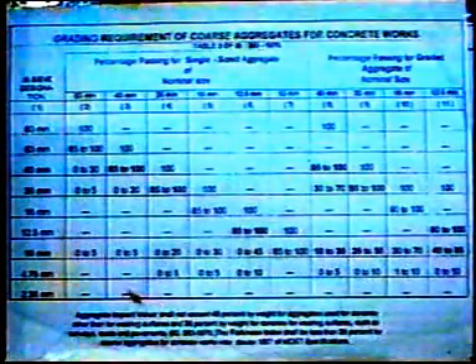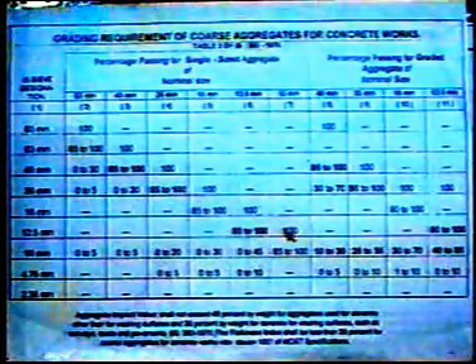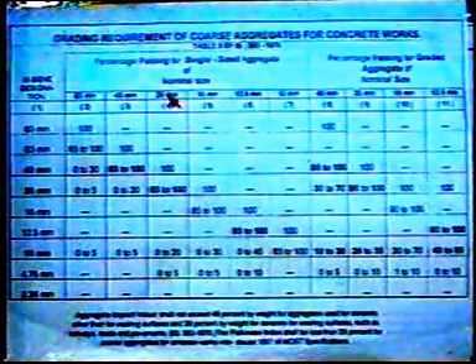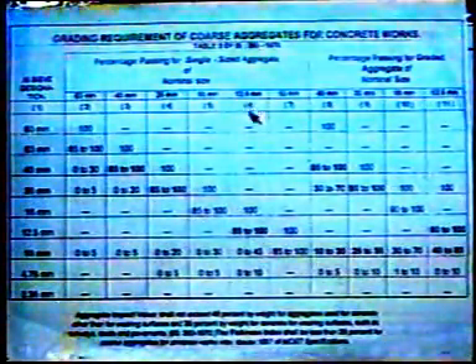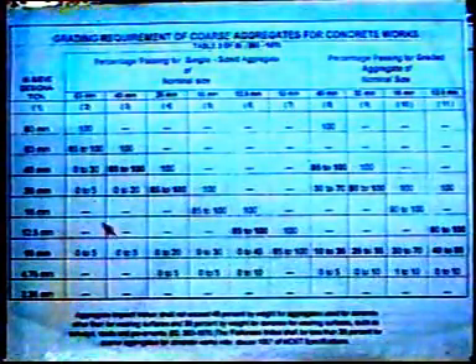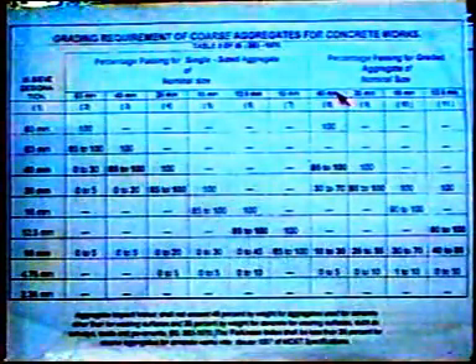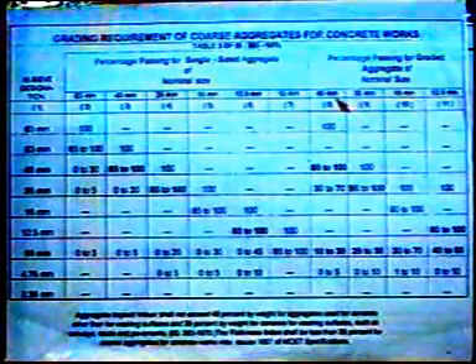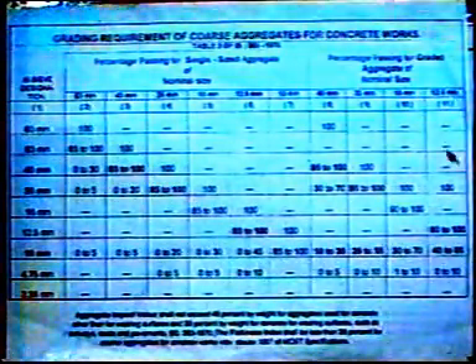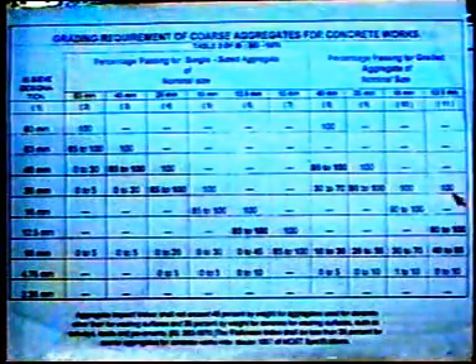The left hand side portion of this table specifies the single sized aggregates to be used in concrete. The 63 mm, 40 mm, 20 mm, 16 mm, 12.5 mm and 10 mm single sized aggregates are covered in the left hand portion. And the right hand portion of the table comprises the graded aggregate details, which comprises 40 mm graded aggregate, 20 mm graded aggregate, 16 mm graded aggregate, and 12.5 mm graded aggregate, which can be obtained by mixing the single sized aggregates shown on the left hand side in different proportions.